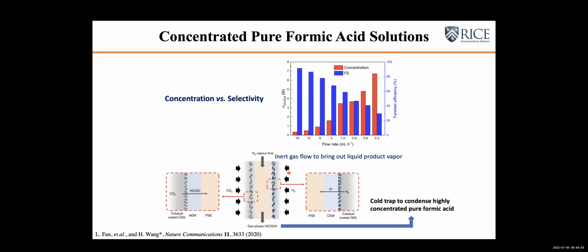In that case, we were thinking about how we can change the DI water flow to an inert gas flow, so that we can continue to flush the middle layer and bring out the formic acid vapor as fast as possible to avoid any accumulation. At the same time, because you have a lot of nitrogen gas, if that goes through a cold condensation process, the nitrogen gas can be separated easily, and the flushed-out formic acid vapors can be condensed to become very high concentration products.